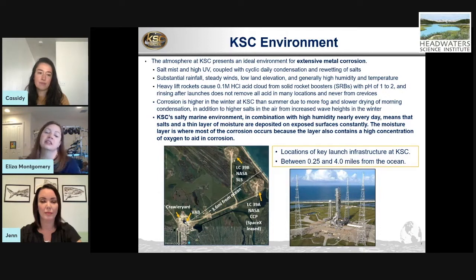And something that I've discovered through my studies that wasn't really written anywhere before, it seems very logical now, is that corrosion is actually higher in the winter than the summer because there is more fog and the temperatures are lower. So the condensation in your fog actually keeps things wetter longer. I counterintuitively thought that the summer was much more corrosive, and it's not at all. It's significantly less corrosive because the heat is so high, it dries things immediately. And then it just kind of stops the corrosion or slows it.